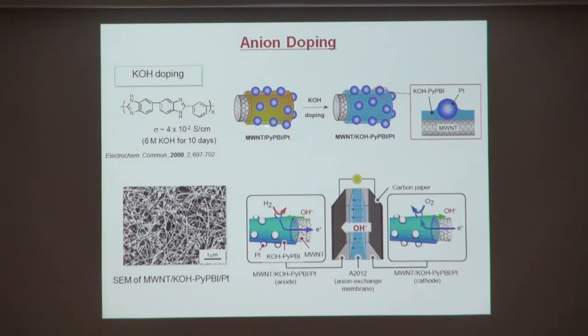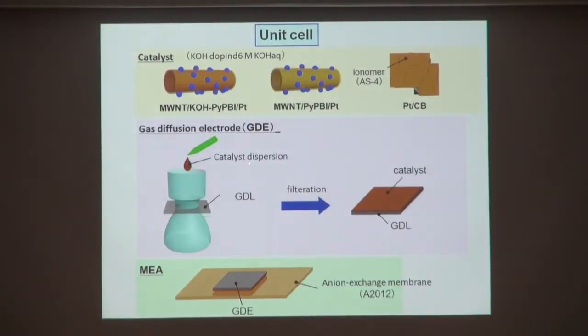I showed our acid type fuel cell catalyst. The cartoon model is like this. And when we dip this acid type catalyst in KOH, we can obtain the alkaline type. This is very simple. And after that, we set up this kind of alkaline fuel cell after making the MEA. And here for the alkaline type, we use not PBI but an anion exchange membrane from Tokuyama company. And here is the KOH doped fuel cell on both sides, and we measured performance by using the GDE MEA.